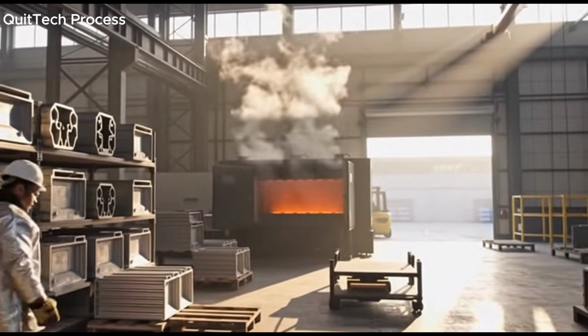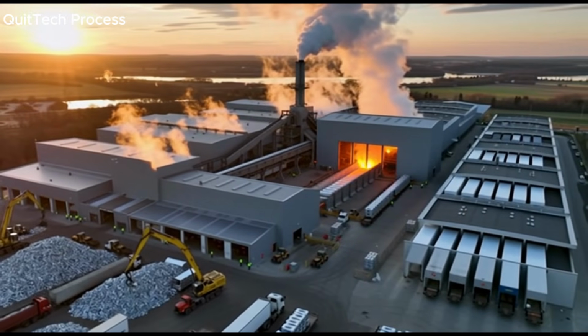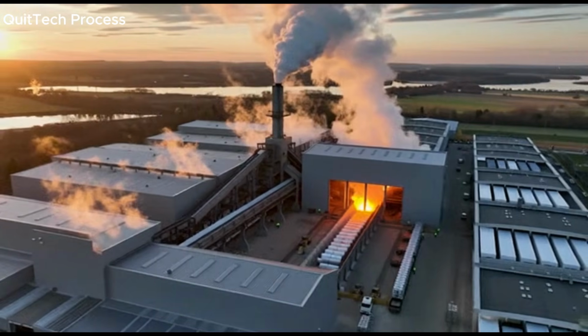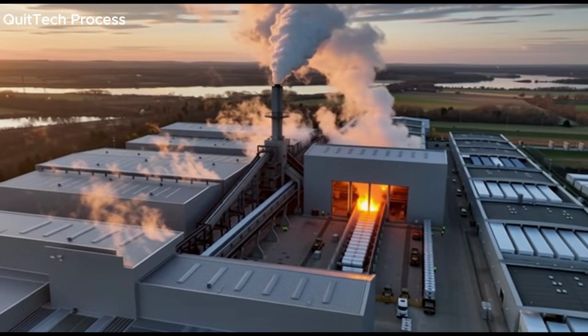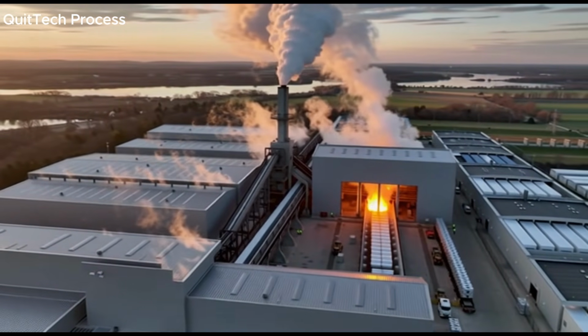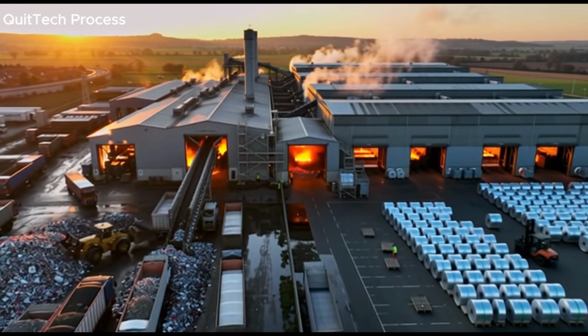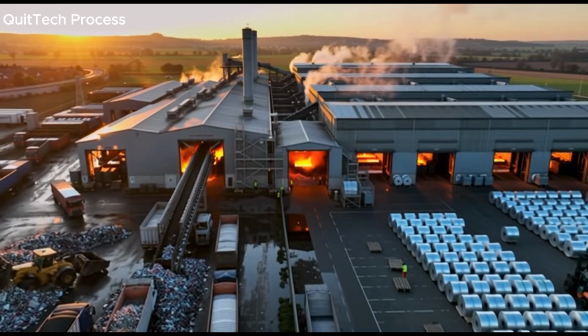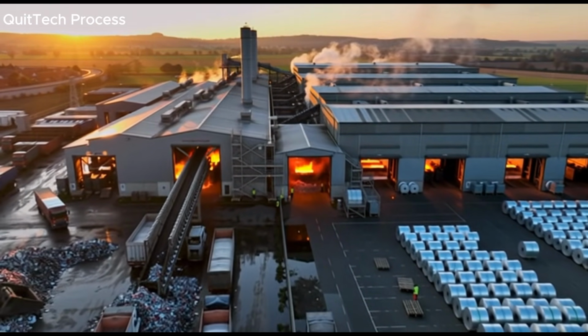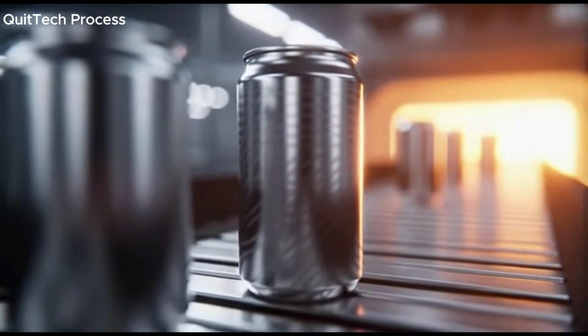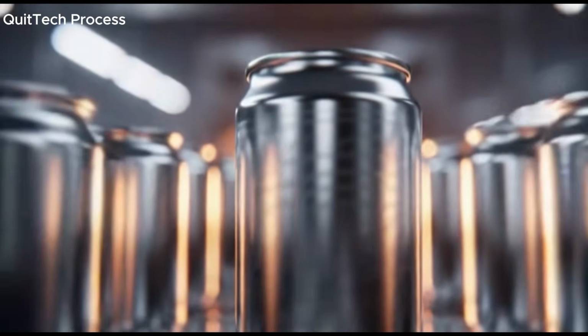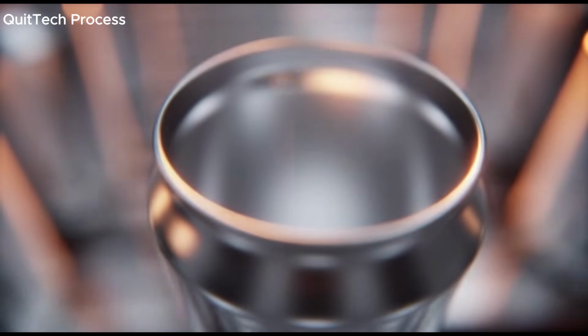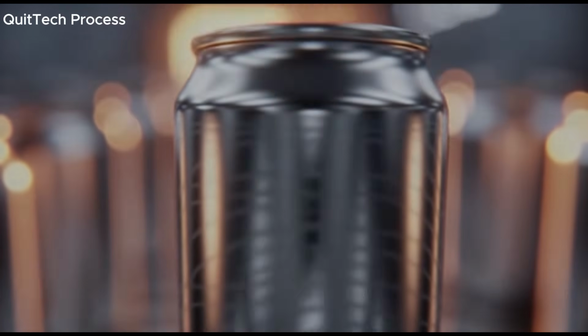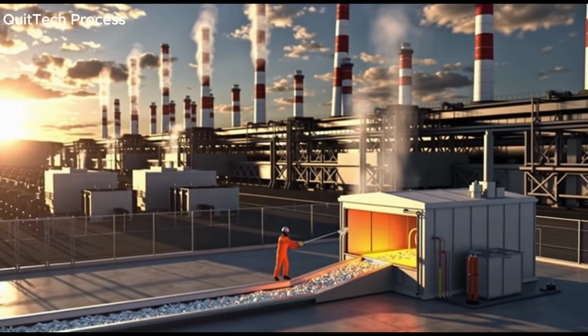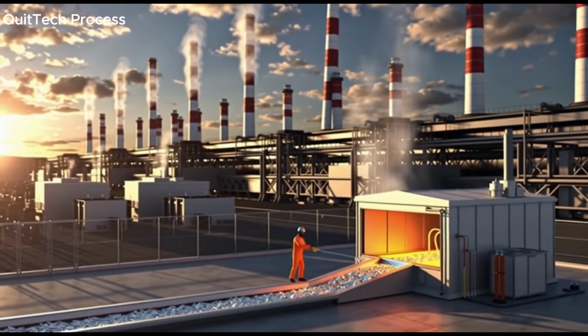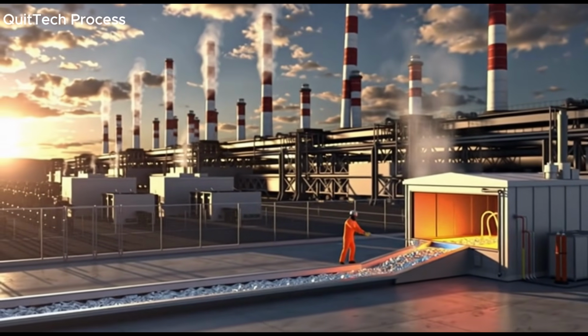Within weeks, the aluminum that was once a discarded beverage can has become a component in a new product, perhaps another can sitting on a supermarket shelf, perhaps a component in an automotive panel, perhaps structural material destined for a building facade or an aircraft fuselage. Aluminum recycled through this system loses nothing. Its structural properties, its workability, its conductivity, all remain fully intact through every cycle. The metal that went through this process today can go through it again in 10 years, and again after that. There is no theoretical limit to how many times aluminum can be recycled without degradation.